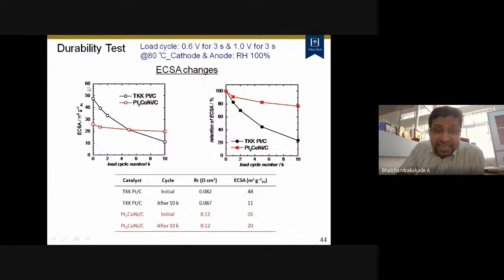You can see that when we measure their electrochemical surface area during stability cycles, 10,000 cycles, the TKK Pt/C is the commercial catalyst. It starts with 48 square meters per gram, and with continuous cycling it reaches almost 10. It's so much loss, a huge loss. It starts with 48 and ends with 11 after 10,000 cycles. Whereas our Pt2CoNi, which is a face-centered tetragonal structure, starts with 26 and ends with 20. So just 6 square meters per gram loss. It means a very, very minimal loss in the ECSA after stability. It means that when I make the face-centered tetragonal structure, I get a stable structure.